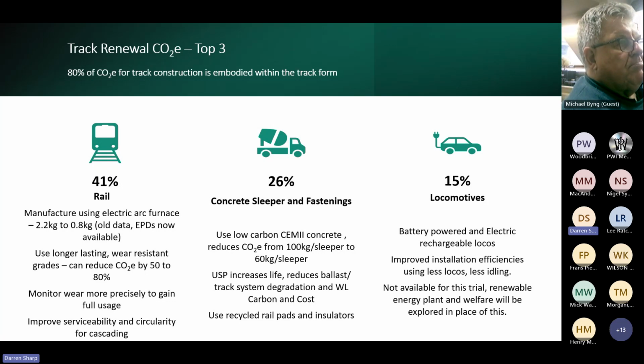With sleepers, we do have low carbon CEM2 mixes that reduce the carbon from 100 to 60, and you'll see some data on that later. There's also other things under sleeper pads to increase the life, reduce the ballast and track system degradation, and that reduces the whole life carbon and cost as well. So there's savings there, and possibly using recycled rail pads and insulators. Locomotives, not part of this study, but we're looking at biofuels and looking at rechargeable and EV vehicles as well, and for staff to site and so on. So it's another area that's being looked into.